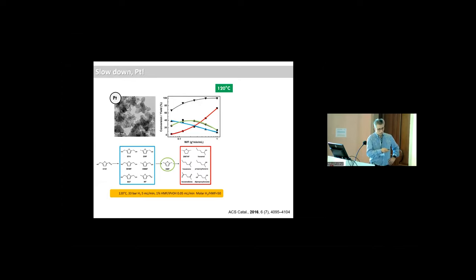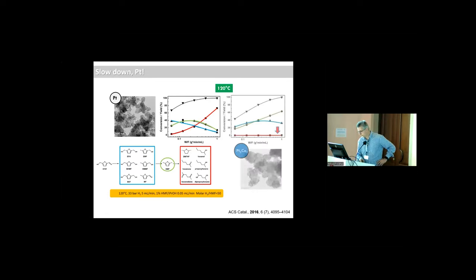Nothing new. We're working in flow conditions, so space velocity can be changed. You can see here conversion increases as you decrease the space velocity, but of course, you go through a maximum in the production of DMF, as you form lots of either blue unwanted products or red unwanted products. If you use the platinum 3, cobalt 2, you can see you can fully stop the overhydrogenation reaction. So you increase the yields in the desired products.